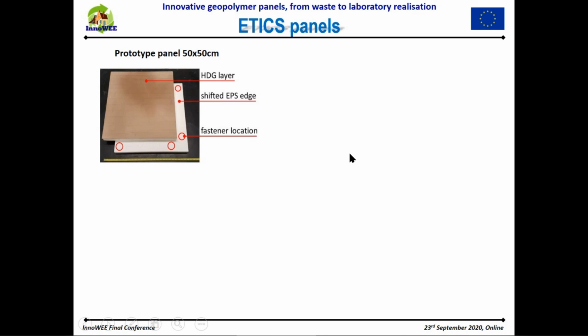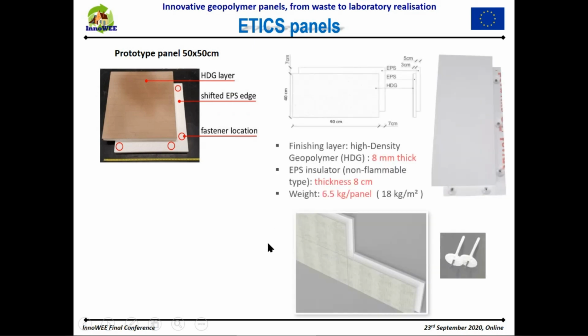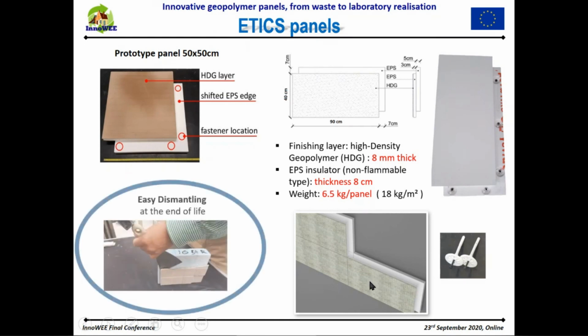Talking about how these panels are constructed, the ETICS measures about 50 by 50 centimeters in the prototype, but in production it was 40 by 90 centimeters, with an external layer of about 8 millimeters of high density geopolymer and internal EPS insulation, with a weight of about 18 kilograms per square meter. It is mounted with special anchors, and the design is particular, with a shifted EPS edge that allows the overlapping of the panels to reduce the thermal bridge. It was also used for easy dismantling at the end of the life of the product.